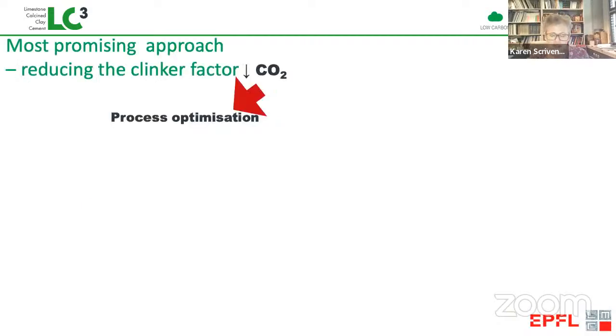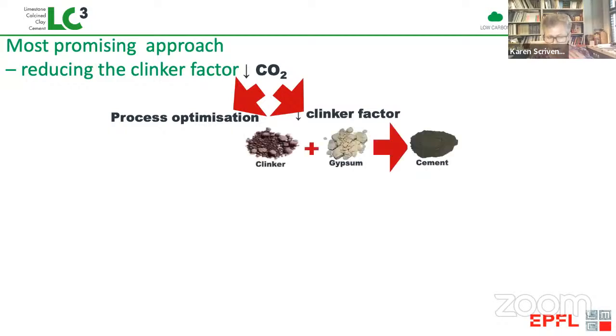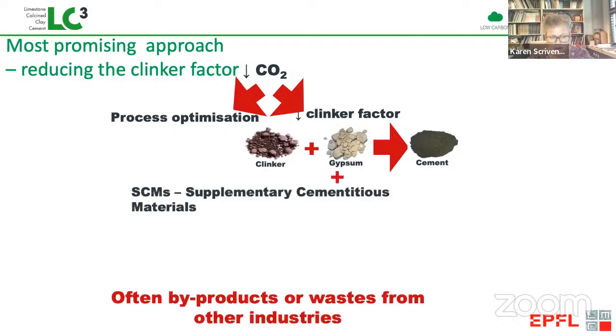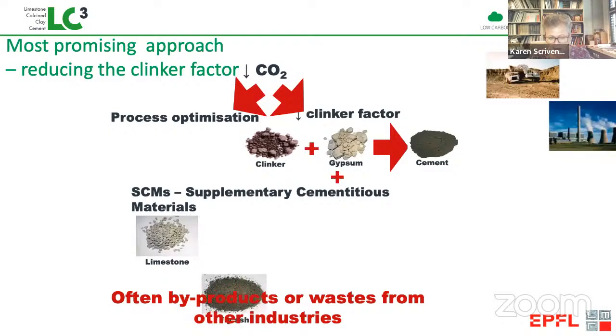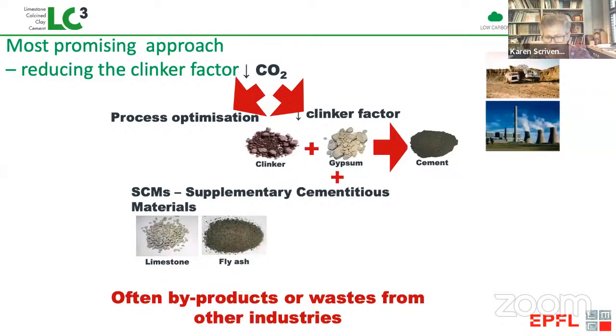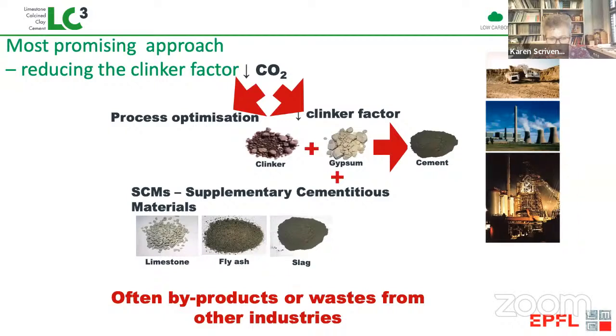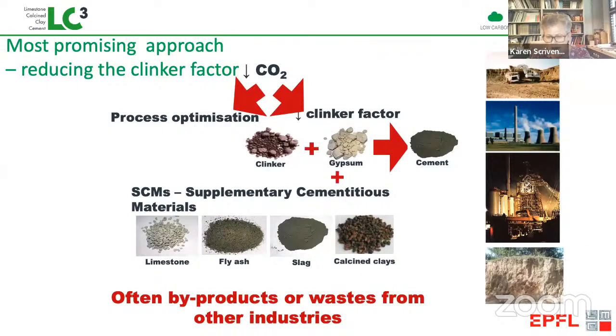So the most realistic option, after, of course, we have optimized the process, which is largely done in India, is to reduce the clinker factor by replacing the clinker we produce in the cement plant with supplementary cementitious materials. This can be fine limestone, this can be fly ash, which comes from burning coal, this can be slag, which comes from producing iron in blast furnaces, and it can be calcined clay.